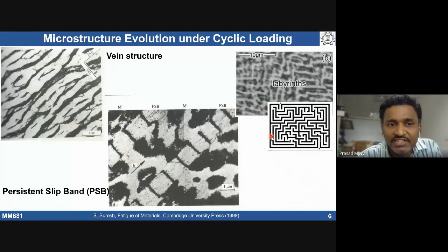So these are examples. In some materials, it was shown that in a single crystal, when you deform, we see this kind of vein structure. Initially there is a low amount of deformation. If you go to a certain amount of deformation, we see formation of persistent slip bands. These bands are relatively low dislocation density regions as compared to the matrix. This is the matrix, and this is a persistent slip band. Again the matrix, and this is a persistent slip band.